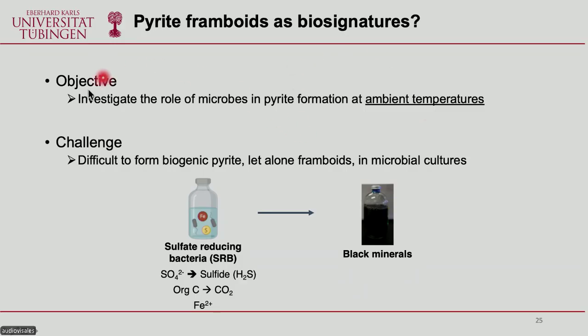And one of the challenges is that we know that it's difficult to form biogenic pyrite in cultures, let alone framboids in microbial cultures. I did this during my postdoc, where it was a complete experimental failure. We had sulfate-reducing bacteria, and I gave them carbon, I gave them iron, and then they formed these black minerals. And these black minerals, I let them sit there for about 2 years, and there was just no pyrite forming, and it stopped at this intermediate species of mackinawite and greigite. And so that was really a failure in the experiment.